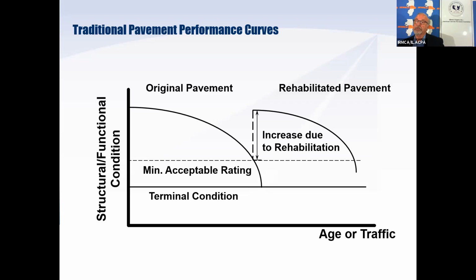But if you'll note the interval between the first curve and the second curve, it's less on the rehabilitation side. The reason for that is that pavements accumulate damage over time. And you can't correct that because it, again, is an accumulated damage, not a visible distress. So what that essentially means is that if I put 1 million load repetitions on the pavement, it doesn't necessarily crack. But occasionally, if I put 1,000,001 load repetitions on the pavement, it will crack. The difference between those two things is what we're discussing here. The accumulated fatigue damage in the pavement is why that second interval is less than the first.